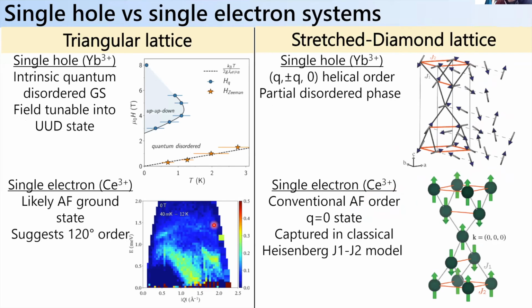So yeah, okay, I'm just going to quickly summarize here. Basically, if I look at single hole versus single electron systems, so this ytterbium 3+ versus the cerium 3+, in these two different lattice types, the key takeaway is the ytterbium 3+ systems seem to be a little special, right? They seem to be fostering these sort of enhanced fluctuation effects, where on the triangular lattice, it seems to be sort of an intrinsic quantum disordered ground state, which has a lot of properties consistent with labeling it as a quantum spin liquid state, some of which I didn't get into. The unique thing about this system is that it does have this sort of field tunable phase, meaning I can drive the system with a moderate magnetic field from a quantum disordered into a fluctuation ordered state and really explore that phase boundary more deeply.